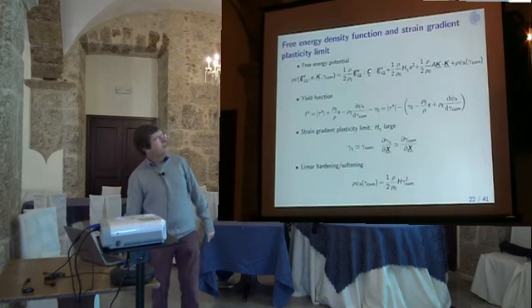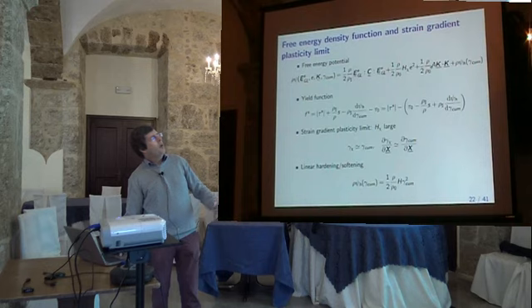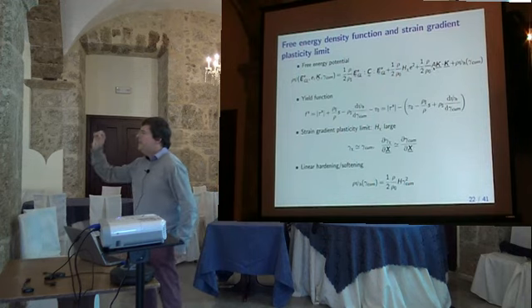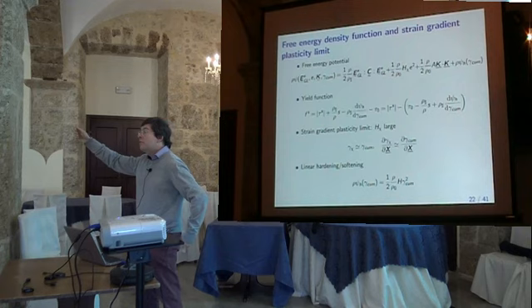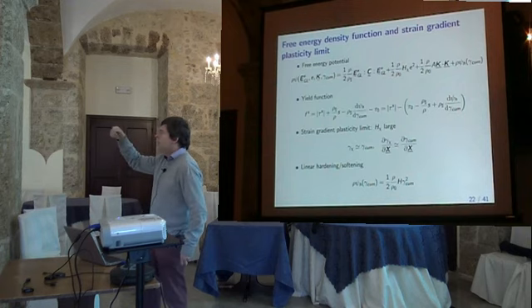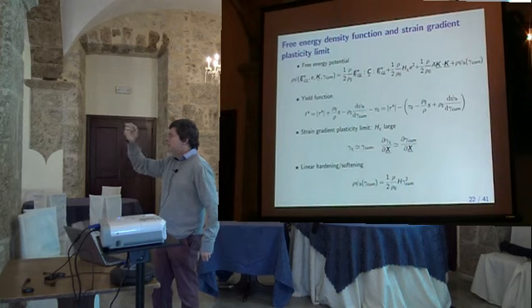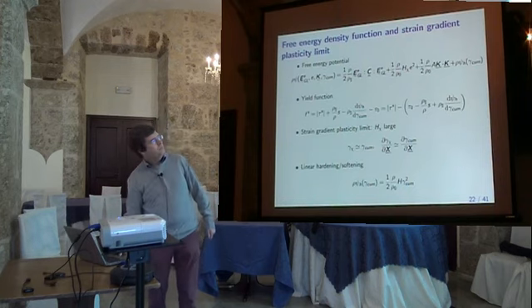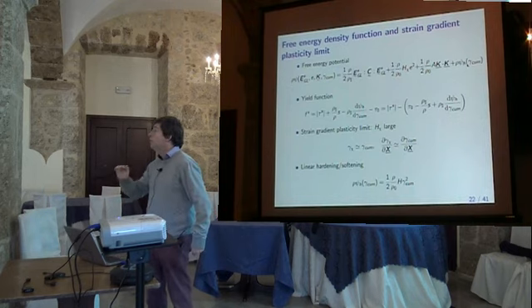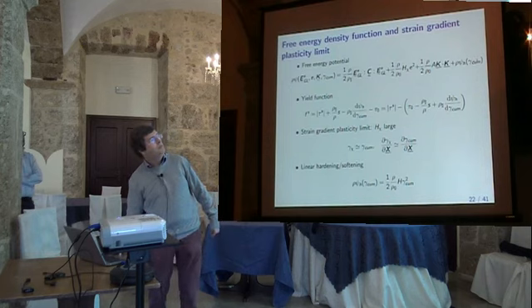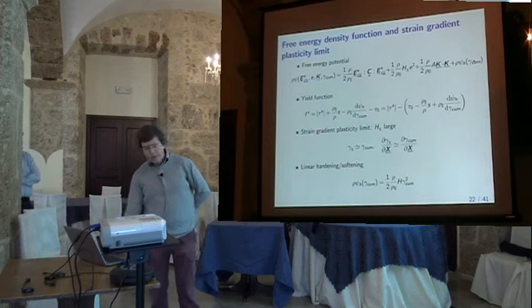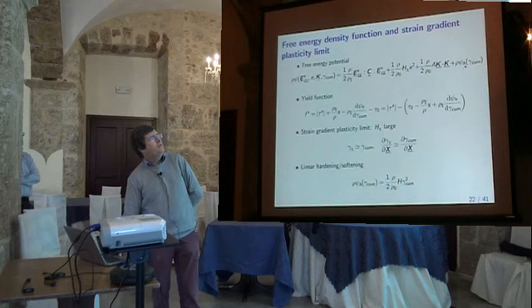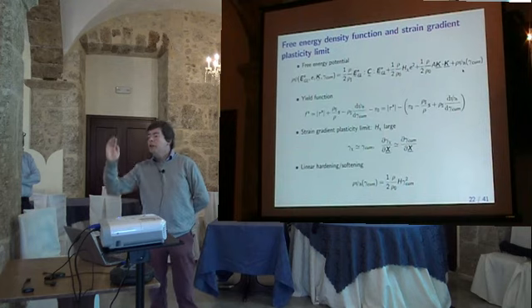So this is the energy I consider, elastic moduli, penalization, quadratic potential with one parameter here, A. So the physical dimension of A is megapascal multiplied by square of the length, so it's Newton in fact. So this is where the intrinsic constitutive length is coded in the model. And then very important, the hardening that I will use, hardening or softening. So this is a function of slip. I will make some choices after, but at the beginning I take a general function. Can be nonlinear hardening.